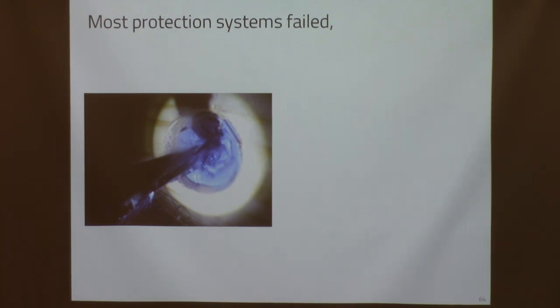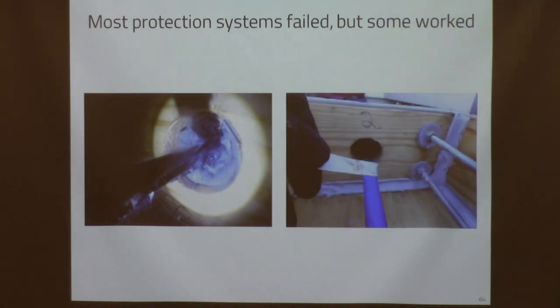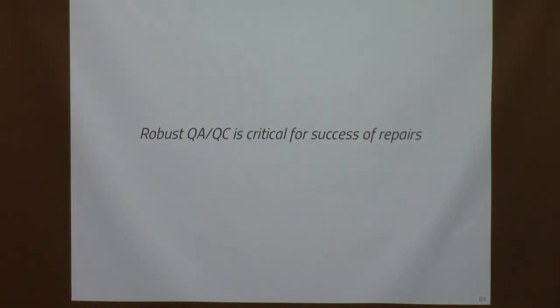So they went through a number of trial and error to figure out what would be the best protection methods. And they finally came up with one that we were comfortable with that they had to put on within, I believe, three days of the exposure, and then it had to be left on until no more than 3 days before they cast the concrete. So, and some of these were exposed for a couple months. You know, they went through and did a lot of demolition work first to get all the debris off, and then they closed them up.